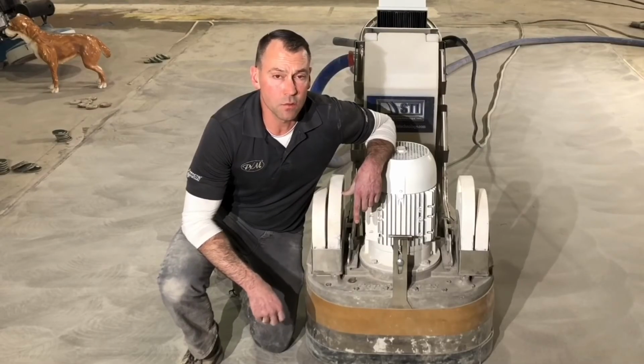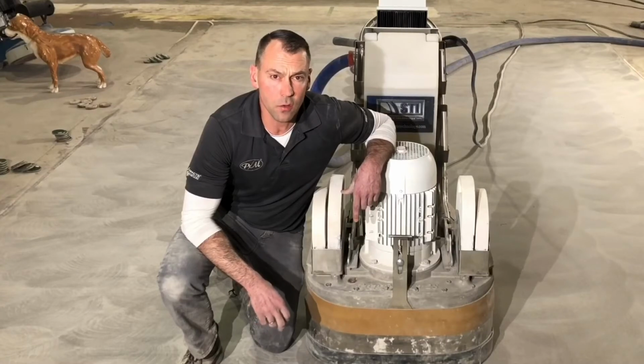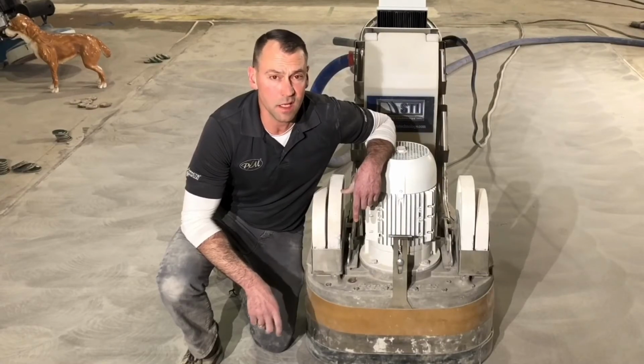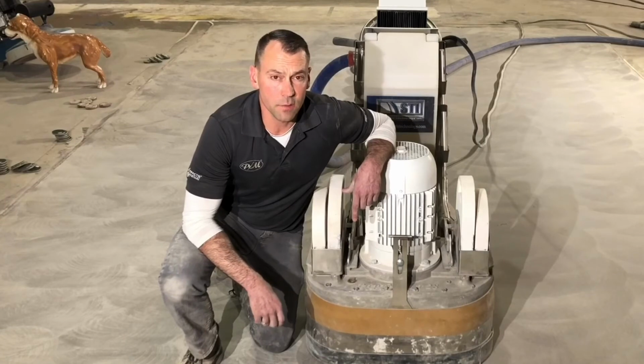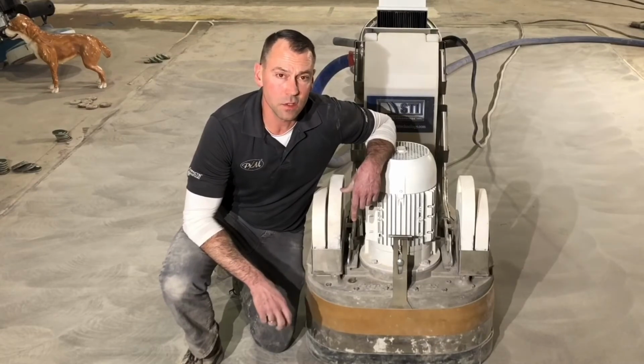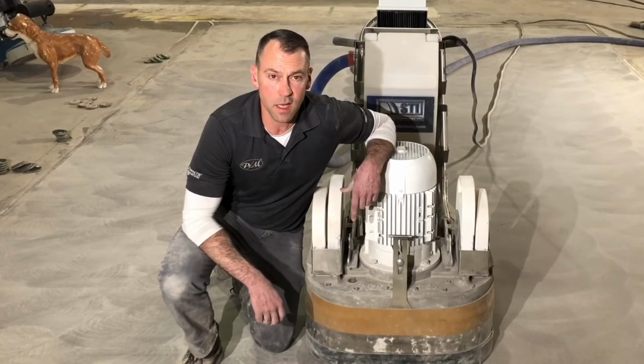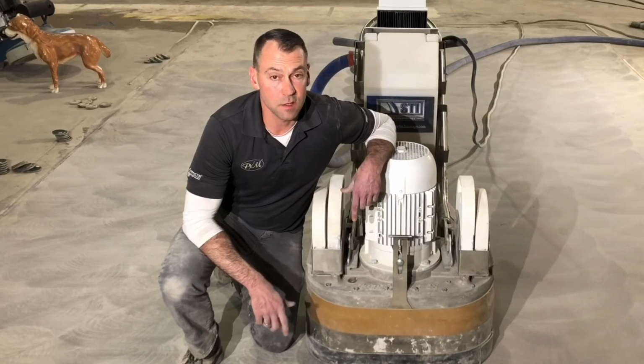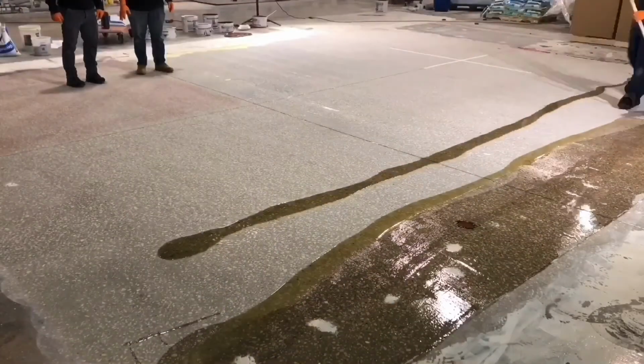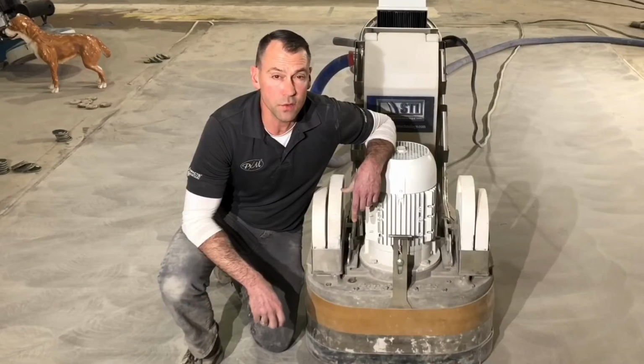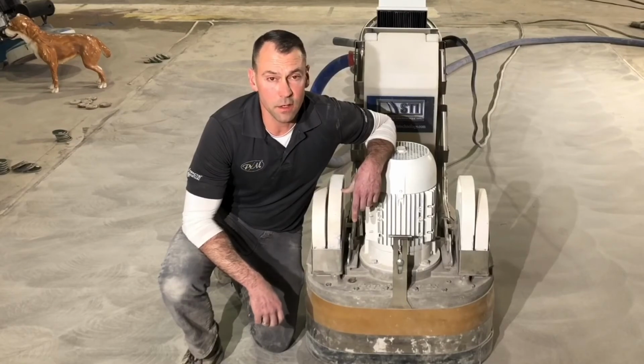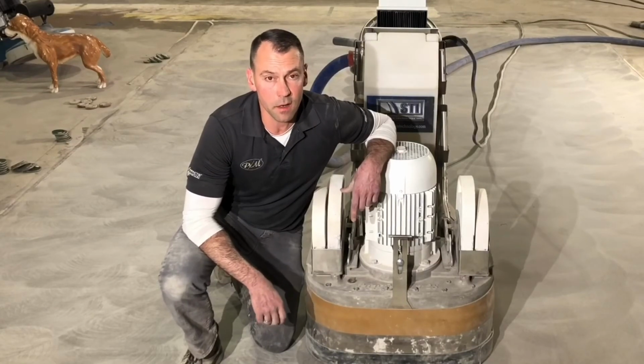As this pad is run over the floor, it's very easy to see the dramatic change from what appears to be scratched and chalky to now looking refined, or almost having a satin patina. And that's just the middle of the polishing process. The vast amount of work that takes place is everything up to this point, but everything up to this point is essential to each part of the process being as efficient as possible. If any part of the process, especially the preparation, especially the primer, which is the most important, that's going to fuse this coating to the slab, if that's not done correctly, delamination issues and cracking are very likely.